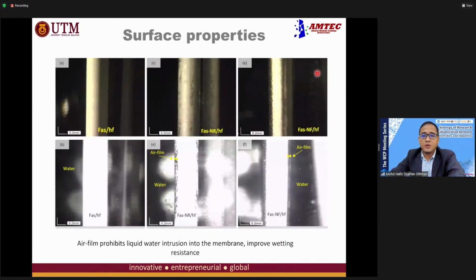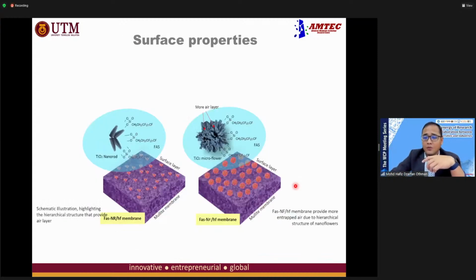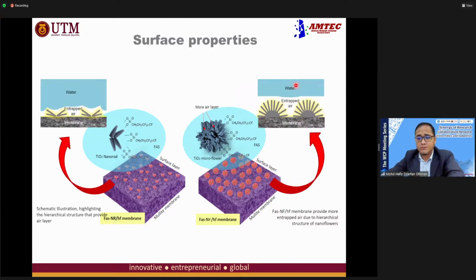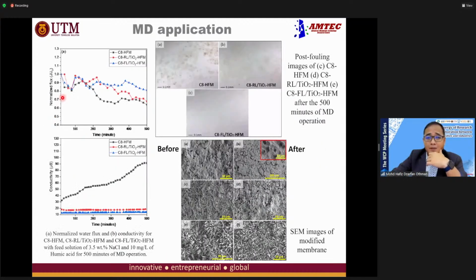We also try to take some photographic images. We immerse the membrane in water, and we can see that the membrane with nanoflower produces an air layer, meaning that this layer will avoid the water contacting the membrane surface. This is due to the hierarchical structure produced by the nanoflower structure on the membrane. Okay. We use membrane distillation again, and we compare with the non-coated ones. We can see that the fouling still happens, but it's not as bad, as there's no wetting at all.